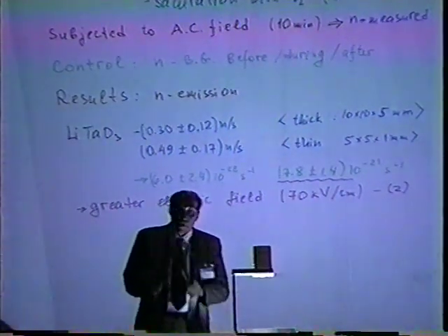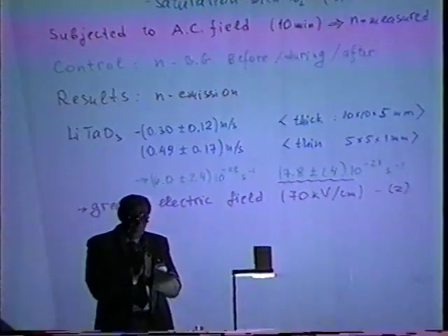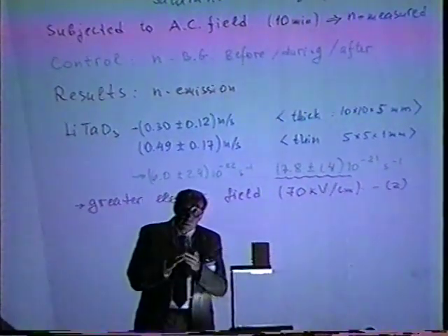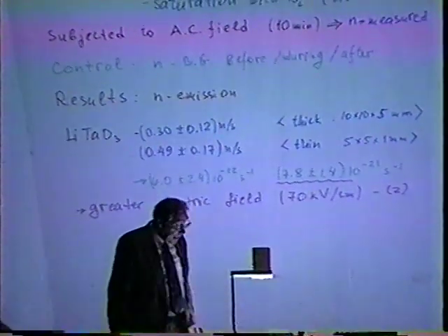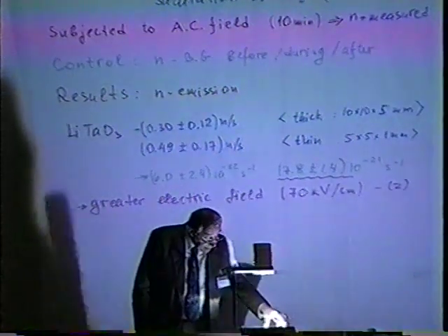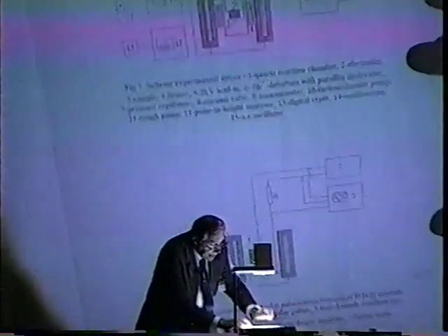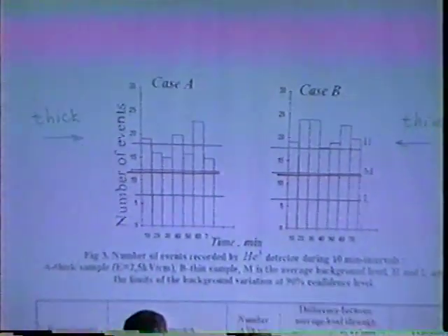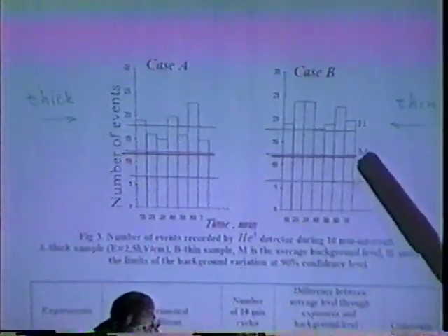And they observed that for a thin dielectric plate, the effect is larger. Probably it's related to a higher electric field in this case. So here is a schematic view of the setup and results. You can see here for thick and thin samples. Red is the average background, and there is some excess of neutrons over background.